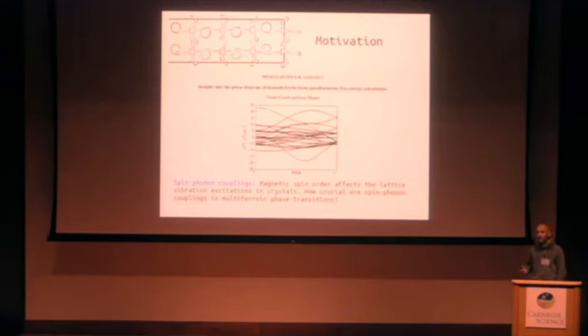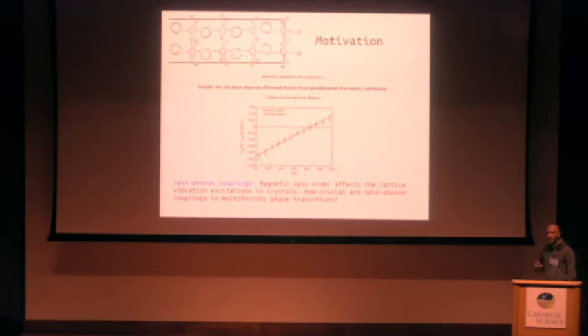That gives you an idea of how important spin-phonon couplings can be. So, as you can see, how the phonon frequencies change when you consider different magnetic order is quite large, right? So we were thinking, okay, if this is big, and this is calculated in the ground state R3c rhombohedral phase, how do these effects affect the phase transitions in bismuth ferrite, right? For that, we developed an extension of the quasi-harmonic approximation based on first-principles calculations, about which I will talk in more detail later, right? In order to take into account the effects of magnetic disorder on the phonon frequencies.